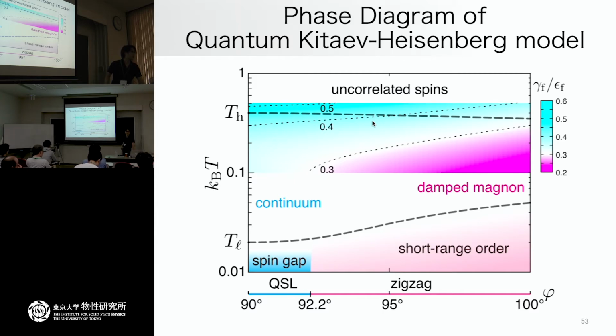In your talk, you mentioned that the other compound, alpha-RuCl3, may not be a realization of the Kitaev model, right? Can your criteria also be used in that case? Okay, so first of all, why I doubt it: if you calculate the spin Hamiltonian from first principles, there are many groups and many results, but we always find that there is a dominant Kitaev coupling, and together with it the gamma coupling is comparable with the Kitaev coupling. So this is the reason why I don't believe the ruthenium chloride is located near the Kitaev limit.